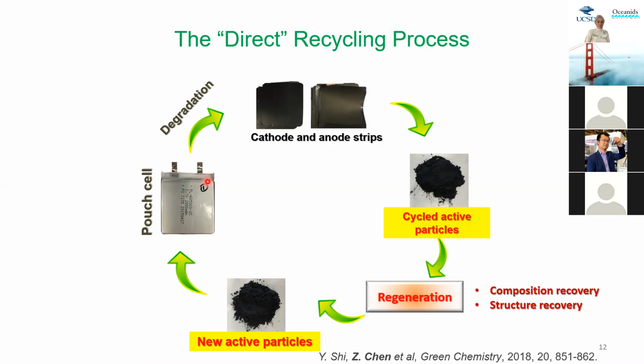So to test our methods, to demonstrate our recycling process, we induce this degradation, and then we open the battery, and then we separate the materials. So actually your electrodes inside this pouch bag will look like this. They're all black. You cannot tell too much. They are all black, okay? Because we use a lot of carbon black to improve the conductivity of electrodes. And then we use some physical processes to separate materials, which we highlighted at the beginning, the metal containing materials, which is lithium cobalt oxide, lithium nickel cobalt manganese oxide. And then we collect this powder, which we call black mass because they are black in color, okay?